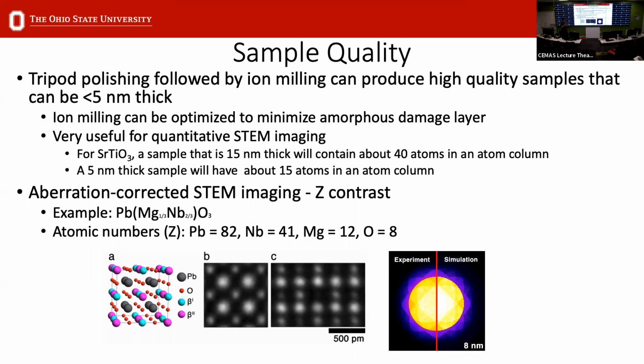And due to Z contrast in STEM, you can see if certain atom columns are magnesium rich or niobium rich. As you can see here in this image, since these regions are short range ordered, if your sample was say 50 nanometers thick, you could have these short range ordered regions overlapping over the entire thickness, and you wouldn't see anything at a higher thickness.